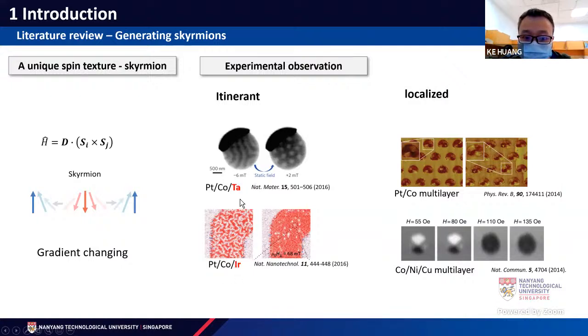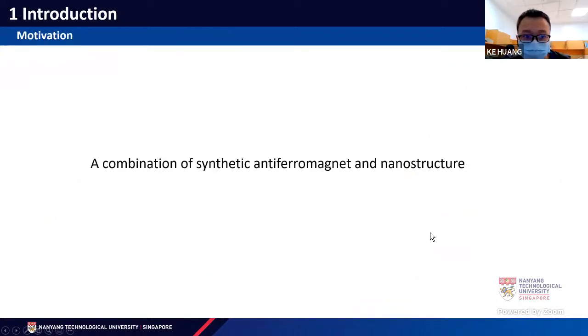Experimentally, to achieve this skyrmion, we need to use heavy metal layers, platinum or tantalum, coupled with cobalt layers, and we can observe this dot-like spin texture, which is a skyrmion. Some other researchers also mentioned that if we etch the layers into a nanostructured shape, like a circular nanodot, we can also observe those very unique gradient transition textures via the nanostructure.